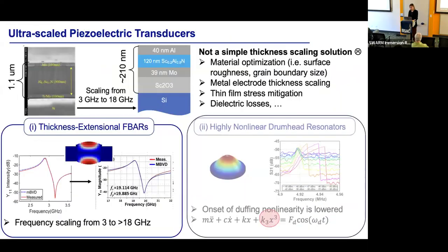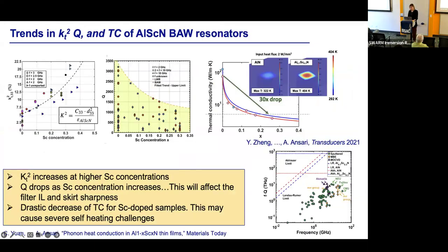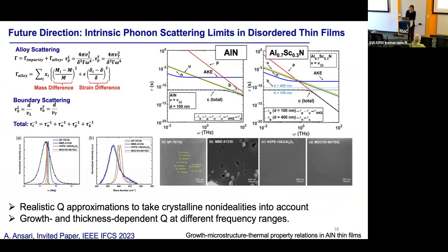However, what I am trying to talk about here is that this Q drop is not only because of your coupling going up, it's because of the scattering mechanisms that are added to your aluminum nitride lattice when you add scandium. The exact modeling is actually a subject of future work, but we know that now you have a ternary alloy, so there's more phonon alloy scattering. We know that a lot of times the crystallinity of the film becomes worse as you increase scandium. Your thermal conductivity is changing. A lot of the material properties are changing. So there are fundamental reasons to have different Qs as you start increasing the scandium content. So it's beyond the Q times KT square kind of material limit.